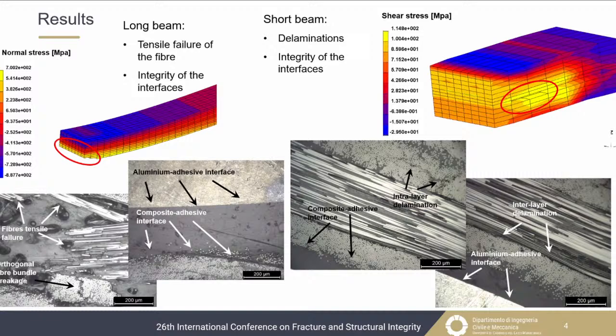And is there any size limit to pass from one typical type of failure to the other, the typical delamination? Usually it depends on the ratio. In the case of the three-point bending, it depends on the ratio between the thickness and the distance between the supports. So we can expect one, the shear stress or the tensile stress, depending on this ratio. Okay, this is very interesting.